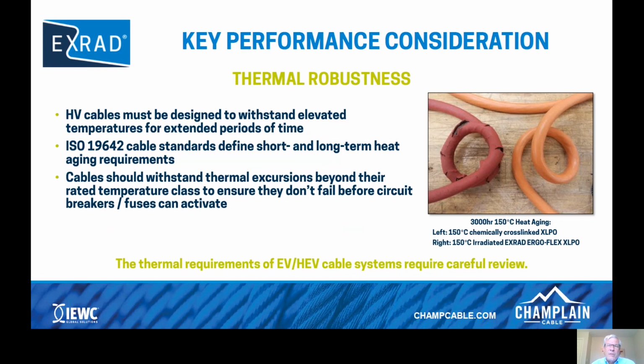So it's not unusual to require a cable to be able to withstand temperatures of 25, 50 degrees above its rated temperature, which is good for the XLPOs because they don't melt. A good takeaway for this is the thermal requirements of an EV or HEV cable system require careful review.